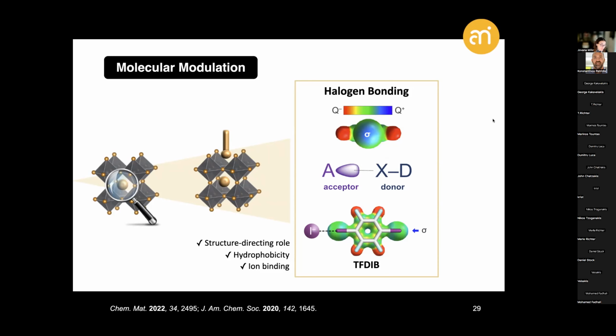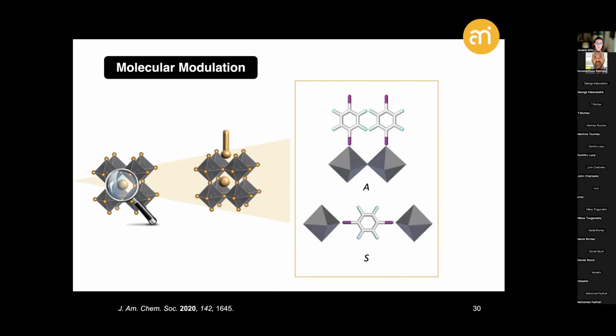Now, in terms of these modes of interaction, based on the characteristics of halogen bonding, we could anticipate two types of interactions that these molecular species could feature in these materials: either this schematically represented asymmetric binding mode through the surface of hybrid perovskite, or this symmetric binding mode cross-linking different perovskite phases, which are defined by this molecular axis separating the fluorine environments that are either inequivalent in the asymmetric binding mode or equivalent in the symmetric binding mode.